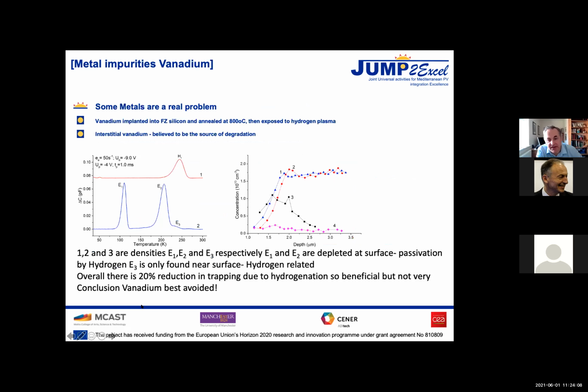Okay, so the other kind of things we used to look at are metals. And so some metals are really, really damaging. So this is vanadium, which is one of the transition metals, which is found in the Earth's crust, obviously, as I said. In this case, we deliberately introduced vanadium. So we took float zone silicon. Float zone silicon is ultra pure silicon. It has essentially no impurities in it by any measure, or almost none, very low impurities, and no oxygen either, actually, or very low oxygen. And then we introduced vanadium by an implantation process, and we annealed it to reform the silicon crystal.